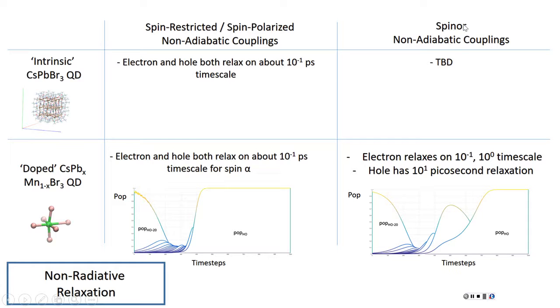But for the spinor non-adiabatic couplings, or if you include spin orbit coupling, you see we populate HOMO minus 20, which is in the perovskite band again, ideally. So it decays, you kind of see some quick relaxation from the perovskite bands. They're a little slower, if you're looking closely, you can look at the time steps. But there's not much of a difference here.